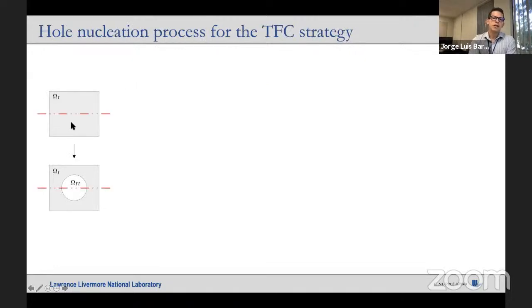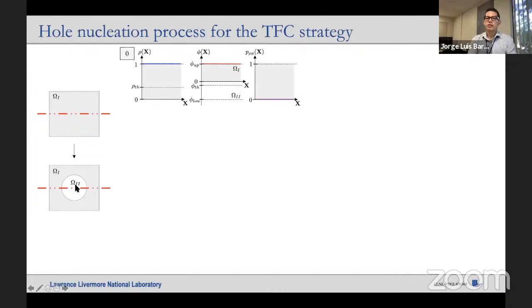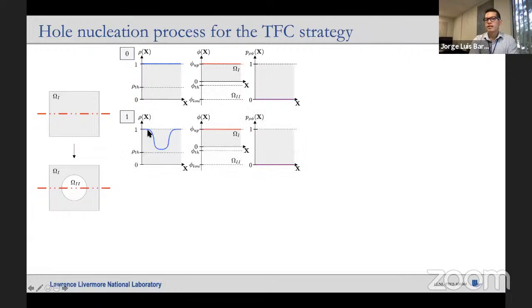Let's look at the 1D example. First I have no holes and I want this hole to be generated. So at the beginning of the process, you have a density of one, the level set field at the upper bound, and the penalty of the two-field coupling is inactive, zero. Because of the problem, the density wants to go down, the problem wants to remove material here. So the density starts going down, but nothing happens in the level set field because the penalty is inactive as long as this density is above the threshold.